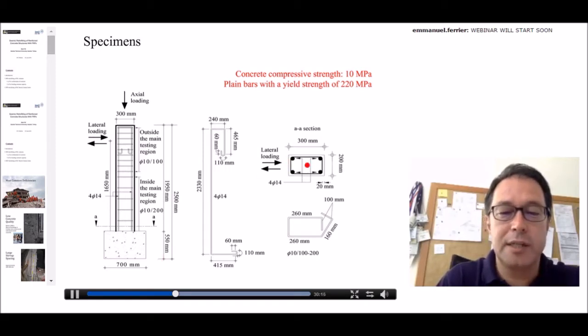So you will see that we are going to add some longitudinal bars and anchor them to the foundation to increase the moment resistance capacity in the potential critical zones. This figure shows the characteristics of the specimens before retrofitting, of course. The column dimensions are like the smaller of the ones I have showed you before, 20 centimeter width and 30 centimeter depth. Again, we have about 1% longitudinal reinforcement ratio, which is obtained by 4 bars at the corners.